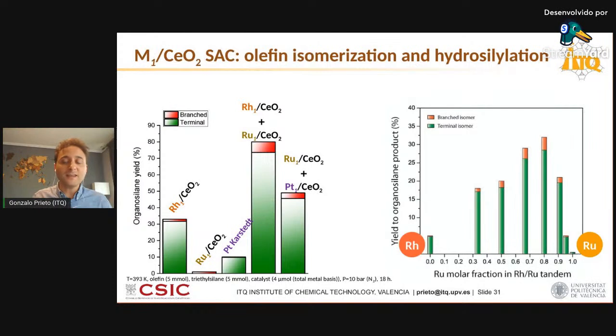Ruthenium and rhodium independently are very poorly active on their own. But then at the optimal catalyst ratio between the two, the ratio that brings very close in value the reaction rates for isomerization and for hydrosilylation, the yield to the organosilanes and the selectivity to the terminal product as compared to the branched one is very high. The terminal is the green part of the bar, the branched is the red part of the bar. Even starting from such a challenging internal olefin as a starting reactant, such as 3-octene.